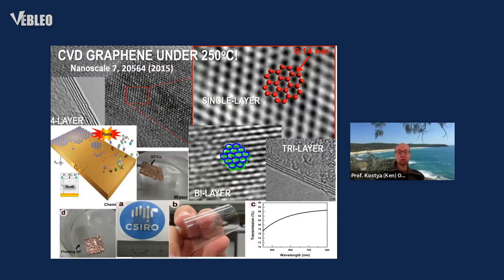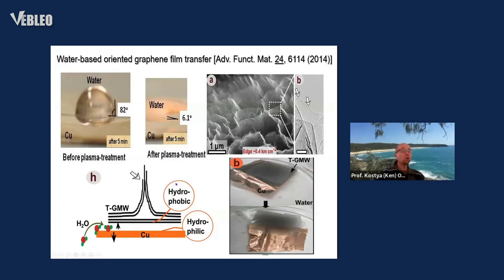There are many other fundamental processes that underpin the unique interactions of plasma with nanoscale objects. And they lead to the formation of various structures, just as exemplified on this slide: single-layer, bilayer, trilayer graphenes, which not only can grow parallel to the surface as flat layers, basically laying on the surface horizontally, or they are graphene-like structures that emerge perpendicular with respect to the supporting catalytic surface, in this case, copper, that they grow vertically and form a network of those vertical structures. We call them vertically oriented graphenes. They are very interesting fundamentally and are utilized in many applications.